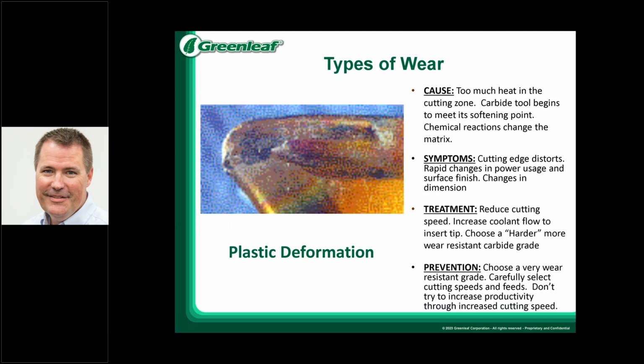This is more common in high temp alloys, although depending on the operation you're running in steel cutting, it could happen as well. If you're running without coolant, this could also be present just because you are not getting that edge cooled throughout the cutting process. Changing to a more wear resistant grade can be very helpful in this. If you are seeing this type, it'll reduce the chance of the plastic deformation, but could lead to other issues of chipping depending on the type of operation you're running.